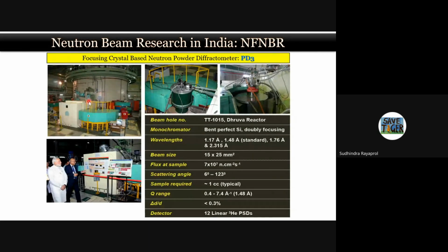Whatever neutrons come from the reactor, we focus them onto the single crystal monochromator, which is our perfectly bent, doubly focusing monochromator. It bends the neutrons and pushes them onto the sample. This is from the point where it comes out of the reactor and falls on the sample. This is a cryogen-free magnet. It is a 7 Tesla magnet. It has an opening window somewhere here, and there is an outgoing window. So what we do is that neutrons fall on the sample, are scattered in the plane, and are taken up by the detectors which are housed in this green assembly.